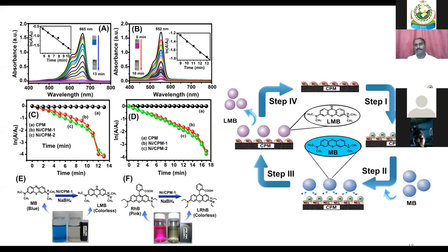These hydrogen atoms are adsorbed on the surface of the catalyst, and methylene blue dye molecules enter in the second step. Then the dye molecule interacts with the proton, that is the hydrogen atom, and finally methylene blue is reduced to leucomethylene blue. It is a colorless solution. It comes out from the reaction mixture, and likewise rhodamine B also follows the same mechanism. This is the mechanism for the dye degradation process.